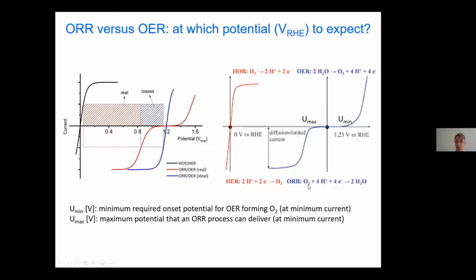That means that O2 can be converted into water and we can generate a U-max. That's the maximum potential that the ORR process can deliver at a minimal current, and we have to define that minimal current. The same we do typically for the OER process. Here O2 is generated if we have the electrodes at a potential U-min, and then the difference between U-min and the 1.23 volts, that will be the overpotential. So we can speak actually of an overpotential for the OER process, and also we can speak about an overpotential for the ORR process.